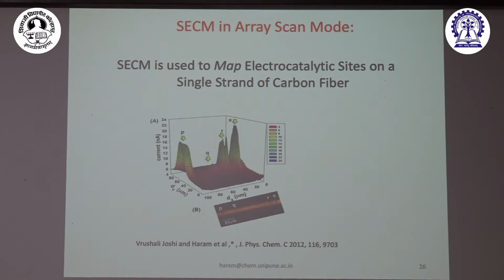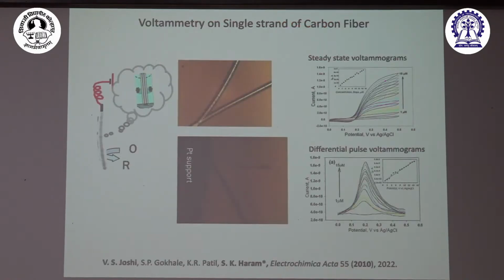Here is a plot of the results. Now we are using carbon fiber of micron size, and we found that it's very active. We made a single fiber electrode like this of carbon fiber when Shivaji was there, when we were doing the experiment. This electrode is basically one strand of carbon fiber, very small. We have to see it under the microscope, thinner than our hair. And then we attached it to the substrate and did a lot of voltammetry to determine dopamine concentration.